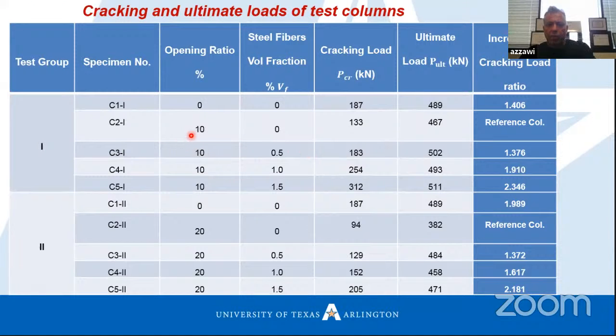If I have a column with 0% opening and 0% fiber, it can carry 187 kilonewton. This is the cracking load. If I provide a hole of 10% and add steel fiber at 0.5%, as we see, I can get the same result. So that means if I have a hole inside columns, I don't need to increase the column size.